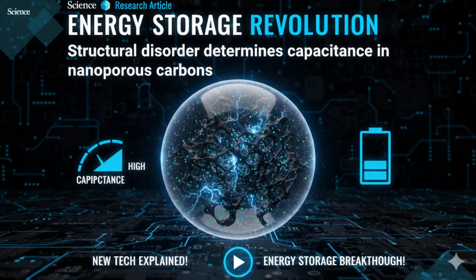Using their NMR method, measuring that Ω value, the disorder indicator, they found this incredibly strong, consistent correlation between capacitance and disorder. It's laid out really clearly in their Figure 2b, and the pattern was unmistakable. Carbons with smaller magnitude values, remember, that means more disorder, smaller graphene bits, consistently showed higher capacitances. And this wasn't just in one type of carbon. It held true across materials from 6 different suppliers, even with different electrolytes. It points at something really fundamental, really universal about these materials.